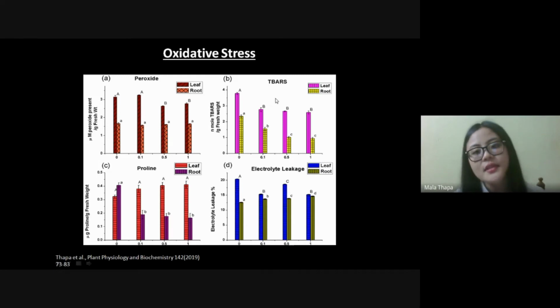Now, an interesting result was found with lipid peroxidation. We found a significant decrease in lipid peroxidation in the treated plant. Lipid peroxidation is an indicator of membrane integrity and damage. So decreasing lipid peroxidation by zinc sulfide nanoparticle confirmed that it acts as protective for membrane integrity.